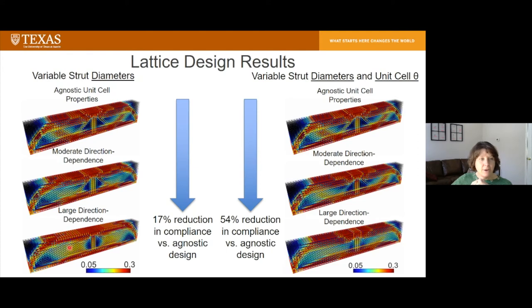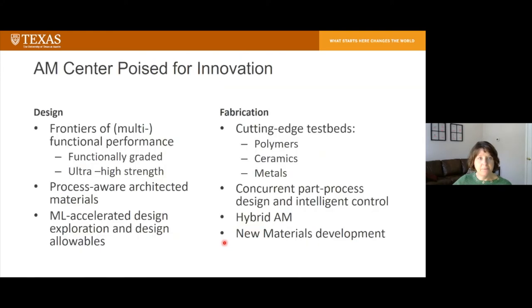And one of the things you'll notice is that when that direction dependence is taken into account, it takes some of the load off of the horizontal struts that you can barely see up here and distributes it more to vertical and diagonal struts, and also distributes that load a little bit more throughout the structure. And so these are types of things that we see, and we get a much better performing structure that performs much more closely to our predictions than we would if we hadn't taken those things into account.